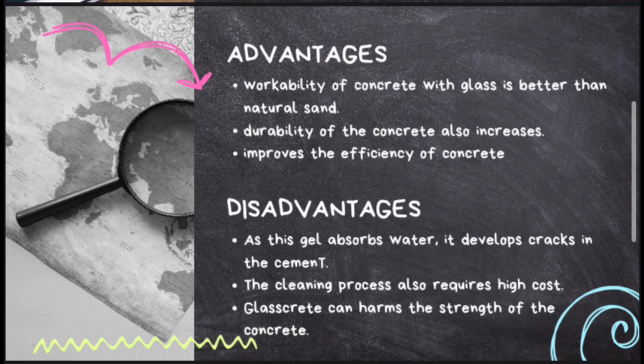The durability of the concrete also increases, and then improves the efficiency of concrete. But the disadvantage of this product is, as this gel absorbs water, it develops cracks in the cement. The cleaning process also requires high cost. Glasscrete can harm the strength of the concrete also.